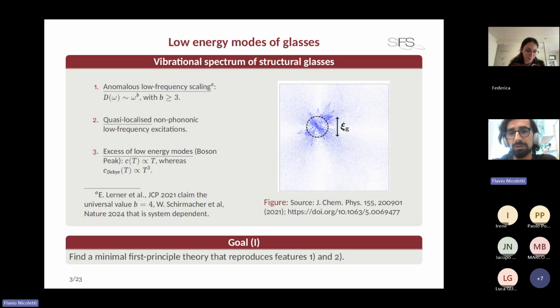Later, in computer simulations of small computer glasses, it was observed that beyond the lowest phononic frequency, there are low energy, non-phononic excitations that are quasi-localized in space, and feature a non-trivial exponent in the lower tail of the density of states. And the value of this exponent is still debated in literature. There are people that claim it has the universal value of 4, that can be derived from the phenomenological soft potential models, which treat locally a glass as a collection of anharmonic oscillators, whereas other evidence instead hints towards a system-dependent exponent.